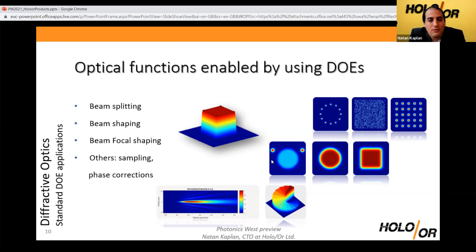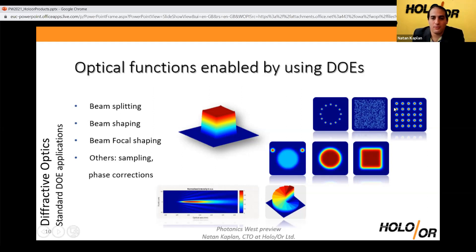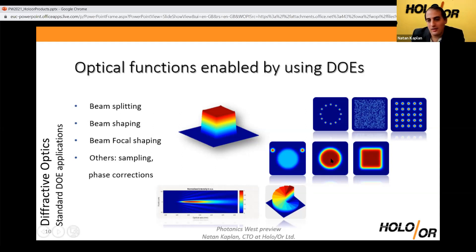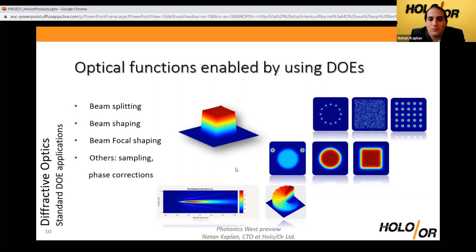There are no NAs like in refractive optics, no curvature, no need to account for that in the AR coating — so they are very suitable for high-power lasers. Typical applications include beam splitting into an array of spots with very accurately controlled separations, one-dimensional arrays for parallel channel scribing, shaping a spot into a flat top using beam shapers or diffusers, creating various mode-changing phase plates such as vortex phase plates, and manipulating the focal characteristics — extending the depth of focus using Bessel-like functions superimposed on the wavefront.